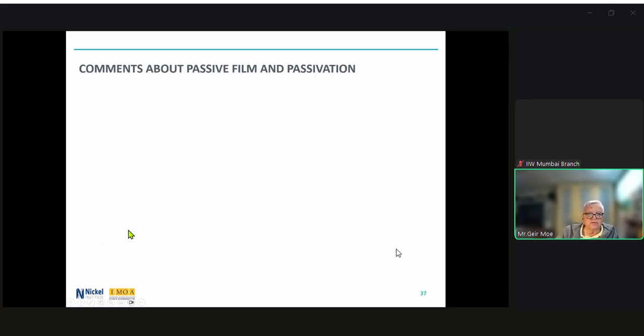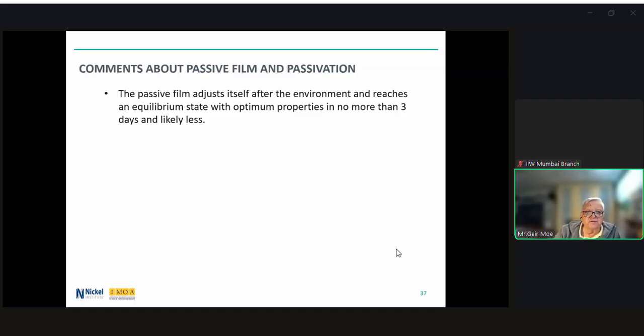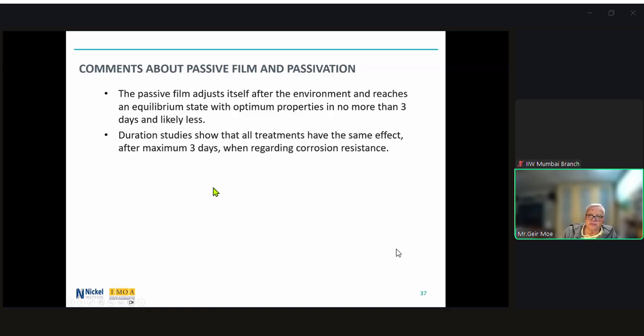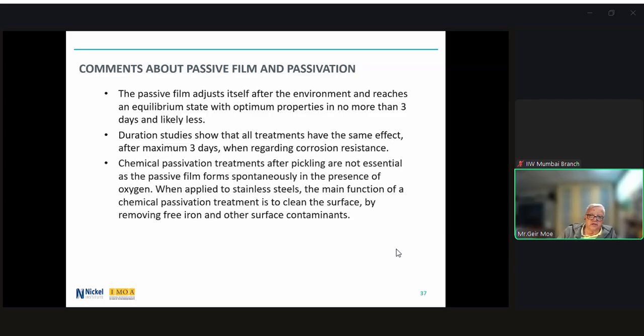So, some comments about the passive film and passivation based on the previous slides. The passive film adjusts itself to the environment and reaches an equilibrium state with optimum properties in no more than 3 days and likely less. Duration studies show that all treatments have the same effect after a maximum of 3 days when regarding corrosion resistance. Chemical passivation treatments after pickling are not essential, as a passive film forms spontaneously in the presence of oxygen. When applied to stainless steels, the main function of a chemical passivation treatment is to clean the surface by removing free iron and other surface contaminants.